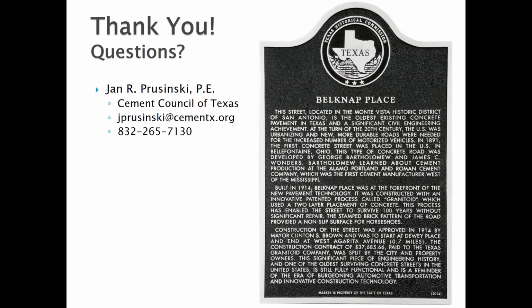There was the specified surface mixture of the concrete to include the 3-part trap rock, 2-part cement, and in the lower one it had the approximate 3-2-1 mix that was specified, but there was no specified strength per se. And we had very limited cores. The cores were not tested for compressive strength based upon the impact echo and what I would use the empirical relationship to strength. I can only guess or estimate that strength is about 4,000 to 4,500 psi.